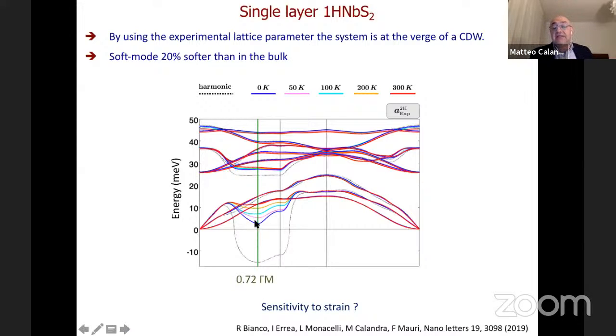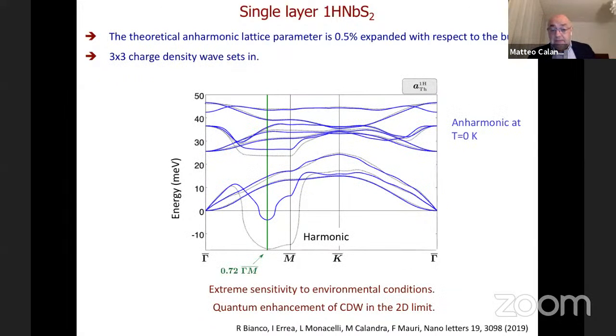It means that this result is extremely sensitive to strain and external perturbation, and a small external perturbation could in principle completely change the situation. So it's very clear that depending on which substrate or which doping or whatever you have, you can easily fall into a charge density wave or go away from it, because this value of the frequency at 0 Kelvin is really, really small. So for example, if you just expand the parameter by 0.5%, you get a perfect 3x3 charge density wave, confirmed even at the anharmonic level, which tells you again about the sensitivity of the system to external conditions.